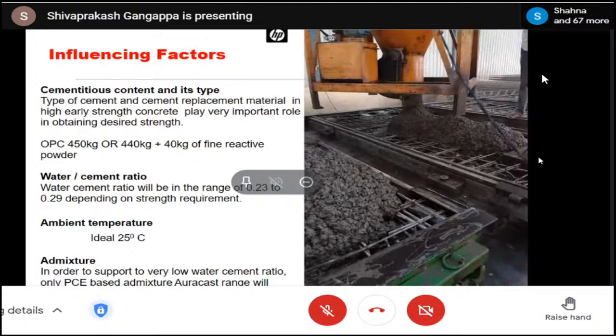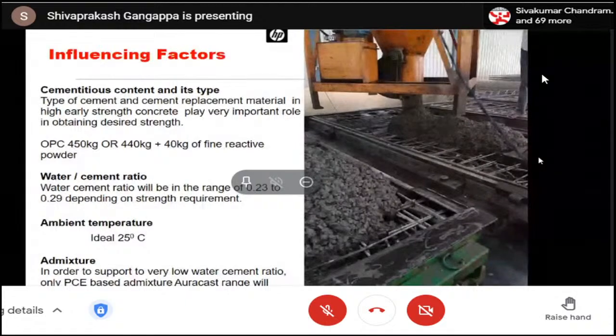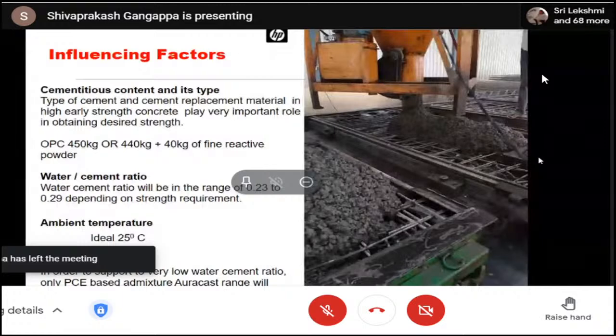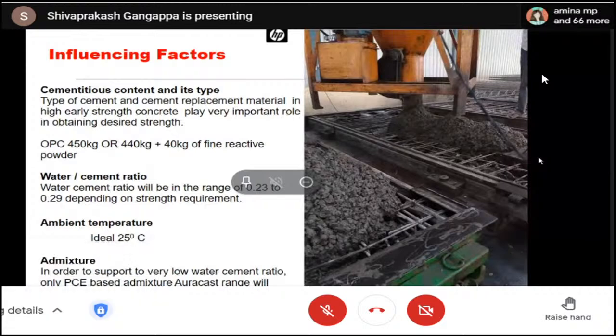Even if you keep adding the powder, the hydration will not take place. That has been mentioned in a few books which I've gone through. Even Brooks and Neville also talk about this particular statement. But there is no rule that you have to restrict to this. If you have room to bring down the water cement ratio less than this, yes, it's possible. But whether the whole quantum of binder content will get hydrated, that's a secondary question. But if it is possible to produce a concrete with water cement ratio lower than 0.28,